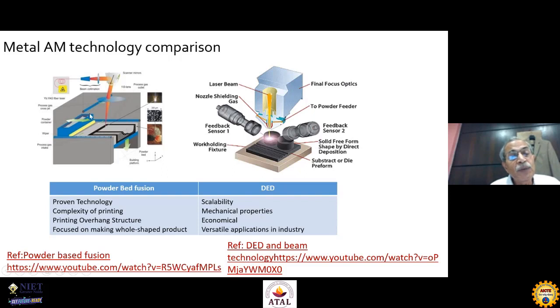With that, you are able to create the geometry on the powder bed, and then the bed goes down, a new layer gets coated, and again the same process is followed as per the geometry. In this, the limitation is that one, maintenance of the laser is a bit of a problem. Two, the moment you have used one type of powder, changeover of the powder becomes a challenge, because you have to clean the whole machine because the powder has been spread all over the place. And since the powder has been placed all over the place, the cleaning becomes a bit of a challenge.